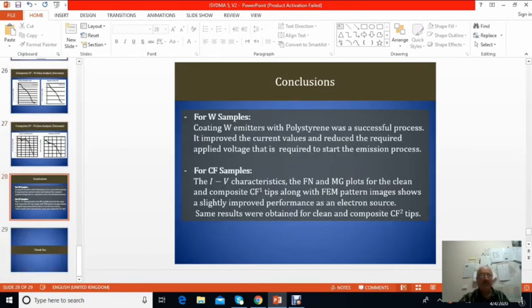And the conclusions: for tungsten samples, coating tungsten emitters with polystyrene was a successful process. We successfully produced the composite emitters. It improved the current values, with a reduced applied voltage required for the same value of emission current. For the carbon fiber samples, the IV characteristics, the Fowler-Nordheim plot, and the MG plots for the clean and composite carbon fiber tips, along with the FEM pattern images, showed a slightly improved performance as an electron source. This was repeated with another set of carbon fibers, different tip radius, and the results were the same.